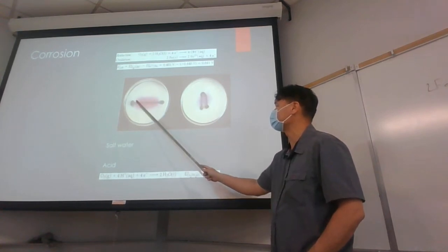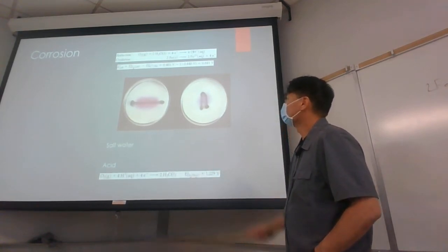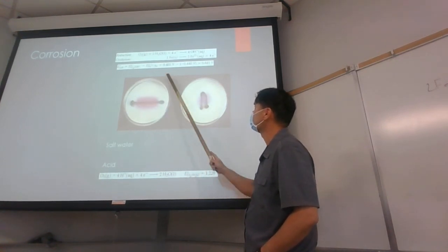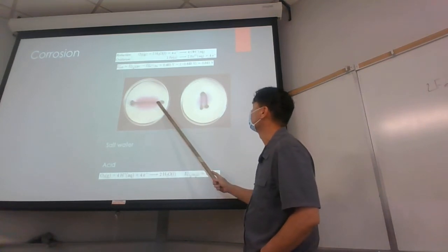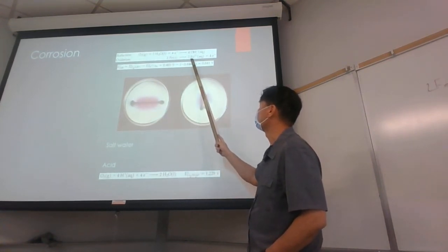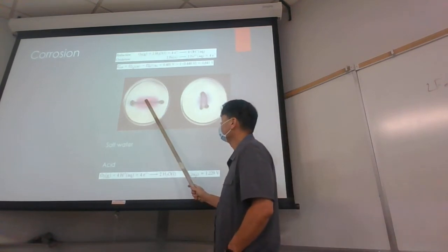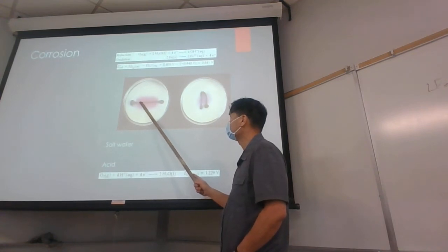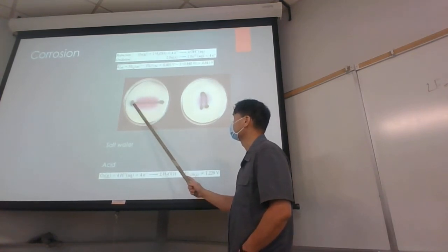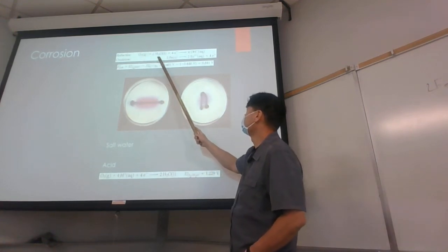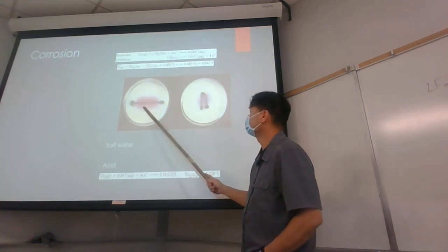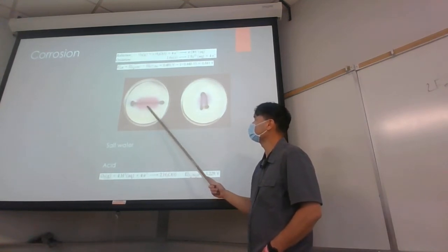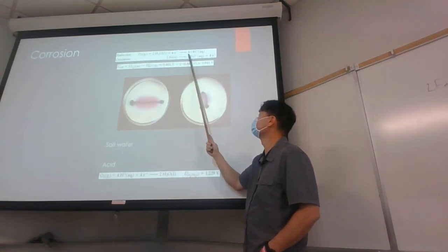So this is just one nail that's been hammered. What we're going to do is oxidize the iron atoms that are easiest to oxidize, and those are here and here. When we oxidize those, we generate iron 2. And then over here, the oxygen comes in to attack and take electrons, but they're taking electrons from the end here. When the oxygens come in and there's water present, we're going to form hydroxide. They put a few drops of phenolphthalein in here, and we can see the hydroxide form here. So this would be the cathode, where the oxygen comes in and forms hydroxide.